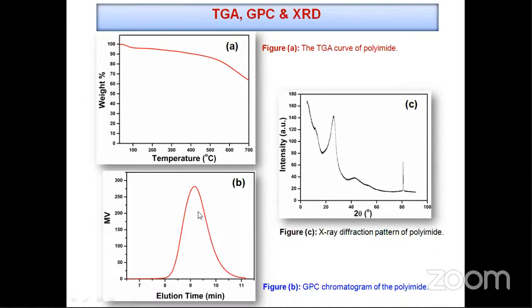This is the GPC chromatogram of the polymer. The average molecular weight of the polyimide was determined with the help of gel permeation chromatography. Here in gel permeation chromatography, the average molecular weight of the polyimide was calculated at 50,380. So the polyimide synthesized by this technique confirms the formation of this polymer.